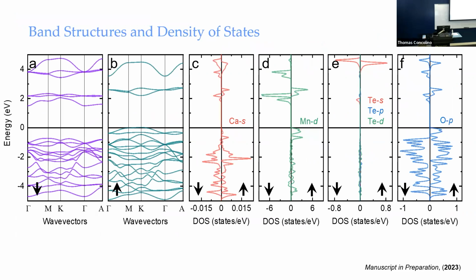If you look here, the band structure and density of states. The band structure is rather diffuse. That indicates that it's more directional, right? Meaning that you have some anisotropy here, and the overlapping of the wavefunction is rather directional. It's not flat. And the Mn d states are polarized, right? Which is direct evidence for magnetism. And then the Mn d states internally polarize the oxygen p states, and you see a very good overlapping between Mn d and oxygen p.